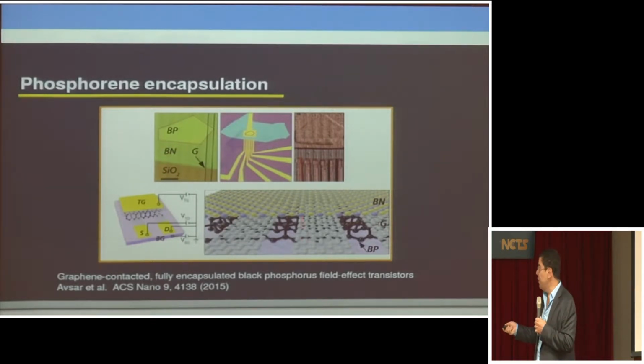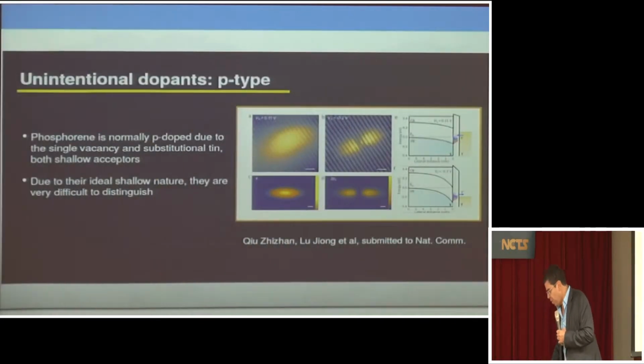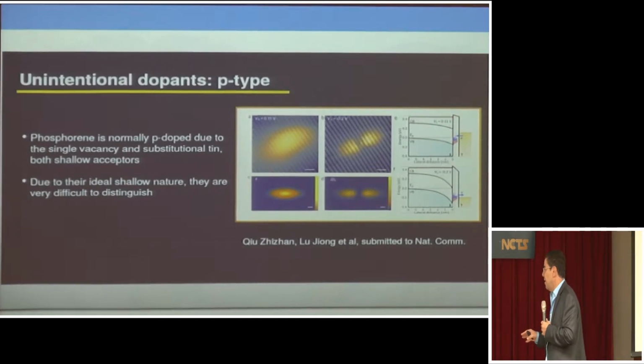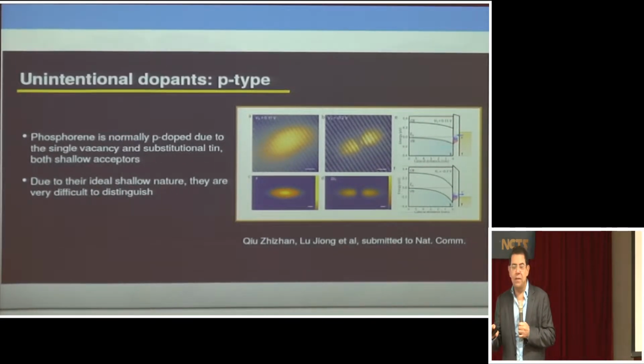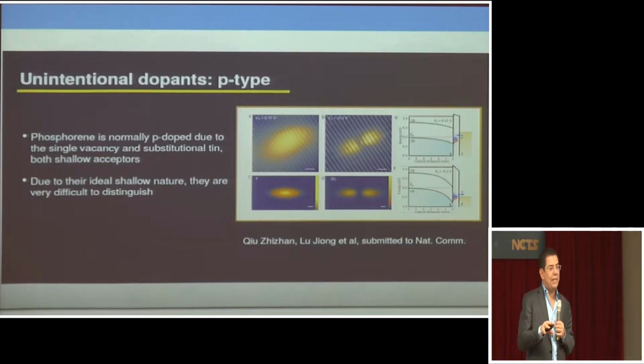Okay? And then what we do, essentially, we lay down boron nitride on top of the phosphorene. Okay? It covers it completely. It's inert. It doesn't change anything in the electrical properties and makes the system extremely clean. And it doesn't oxidize anymore. So actually this was proven experimentally in our labs. Another thing that is very interesting is that sometimes we find defects in this material that we didn't expect before.